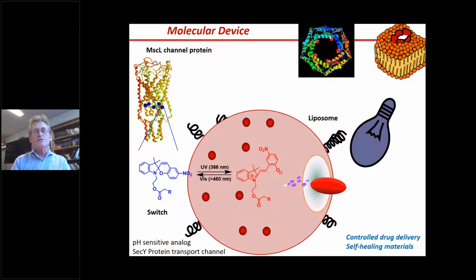You see here a typical switch, which is called a spiropyran. You can switch it with two wavelengths of light between a closed and a so-called open state. And in the red open state, you see charges. The molecule is much more hydrophilic. So we thought charge repulsion, dipole repulsion, and water will be attracted into the pore, and we can open it